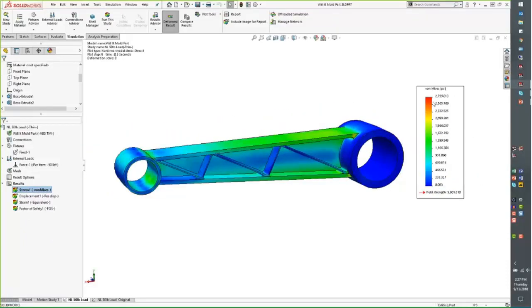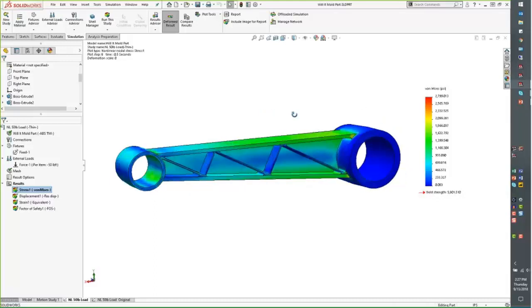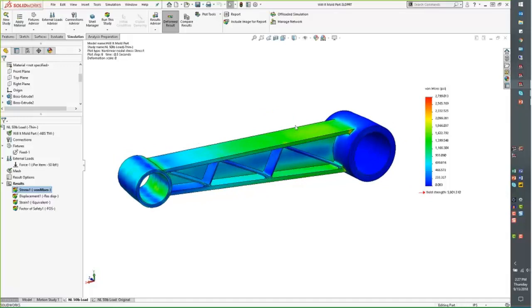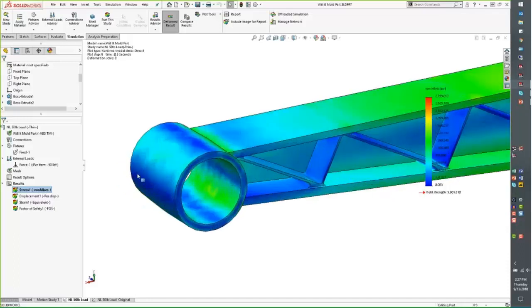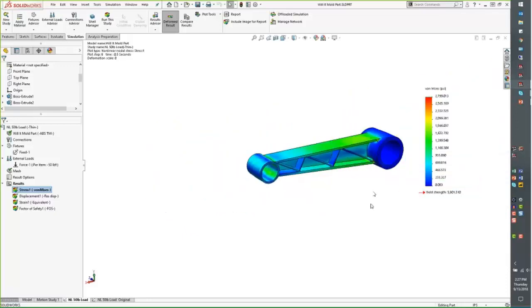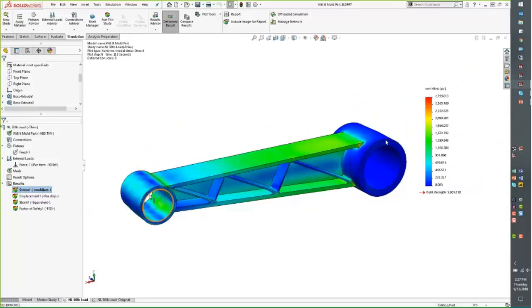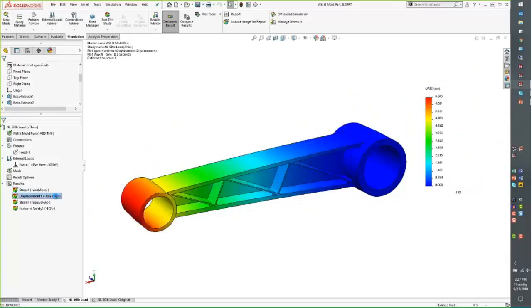So we're right around 2,799 PSI. So our stress did go up, and it did go up because it's a thinner part. It's able to move a little bit more, which equates to a higher stress value. I do not see high stress in this area where my cursor is, and that's a good thing, right? If we saw high stress here, then we would need to look at what's going on with those knit lines. At this point, we feel okay. That knit line is not in the high stress area, so we should be all right structurally from that standpoint. We can look at the displacement. The displacement did go up, but maybe 8 millimeters is our cutoff, so we're still well within that.